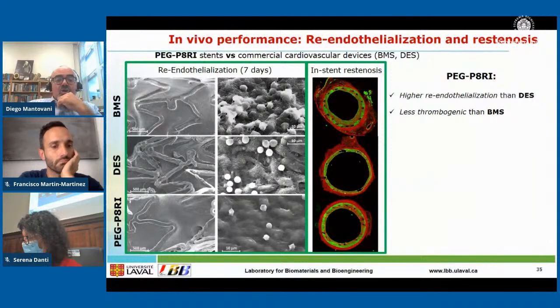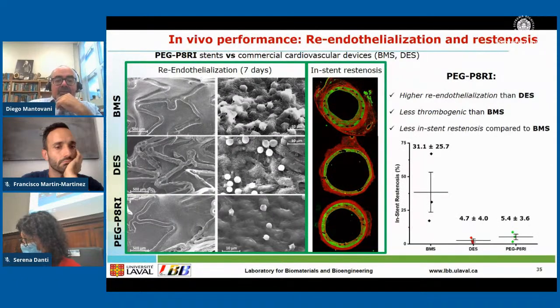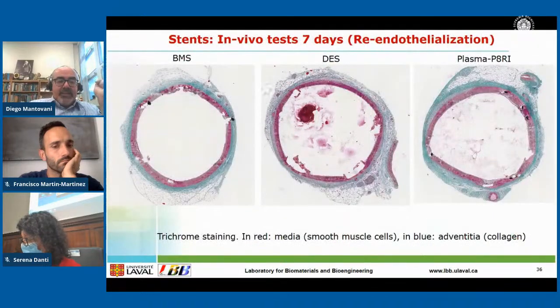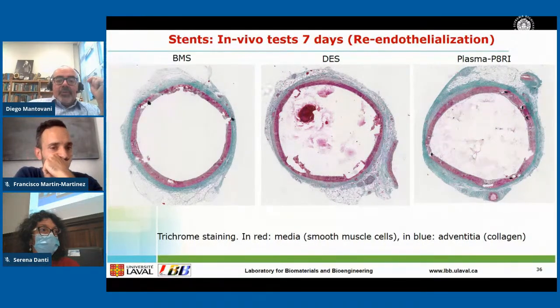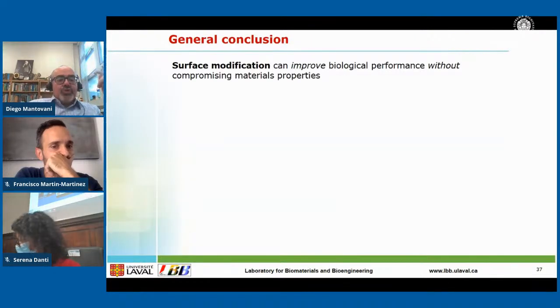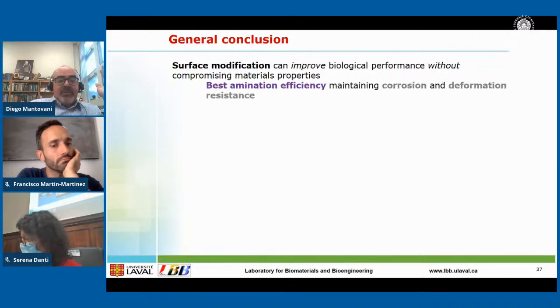This is an OCT image where you see the patency, and basically you see that the drug-eluting stent is not bad at all, but the best is really the peptide-coated stent. So there is less in-stent restenosis compared to bare metal stent. And this is the in vivo test 7 days after, and you can see the bare metal stent with basically no coagulation, some coagulation here in the drug-eluting stent, and finally the plasma peptide-coated one, quite clean.